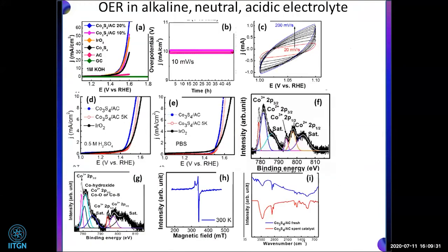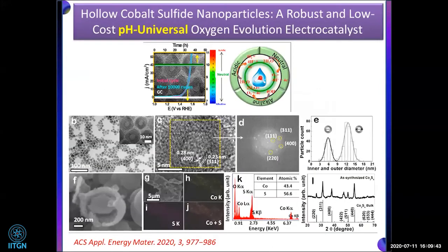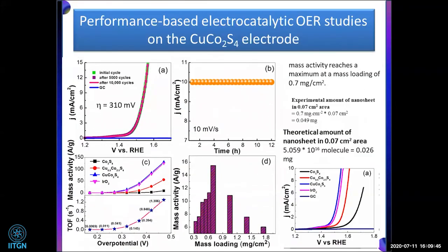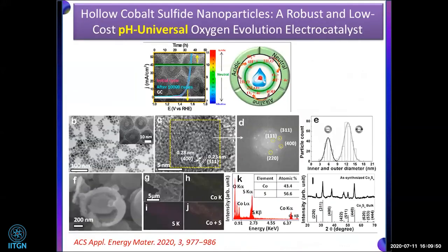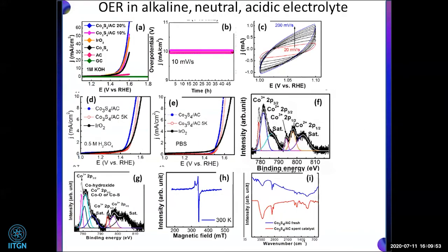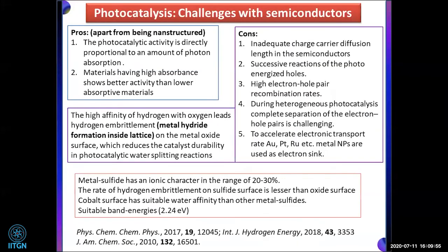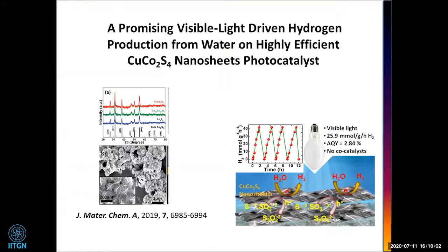electrocatalytic hydrogen evolution reaction, water splitting reaction, the catalyst used should have an almost metallic character. It should have high conductivity. I have not shown it here, but we have done an EIS study. From the impedance study, we found our copper cobalt sulfide is a good conducting material. Then, as copper cobalt sulfide is a chalcogen material, it should be a semiconductor also. So with the same synthesis and characterization, we started characterizing the semiconductor properties.